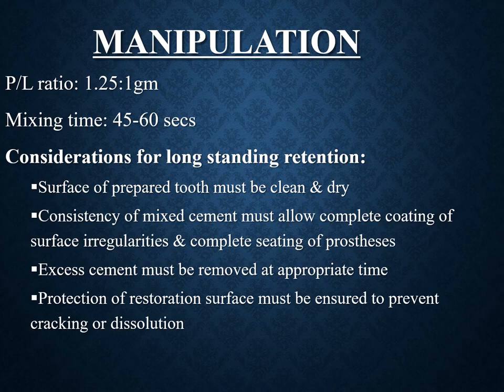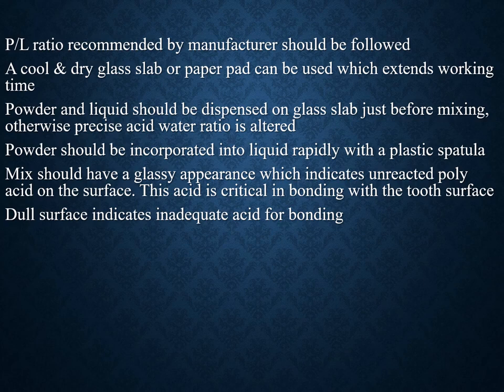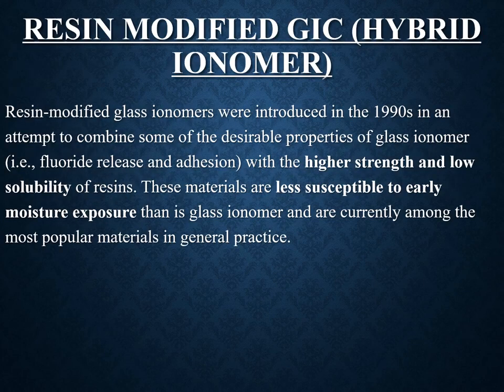Protection of the restoration surface must be ensured to prevent cracking or dissolution. The manufacturer's recommended powder-to-liquid ratio should be followed. A cool, dry glass slab or paper pad extends working time; powder and liquid should be dispensed before mixing, otherwise the acid-base ratio will be altered. Powder is incorporated into liquid rapidly with a plastic spatula; the mix should have a glassy appearance indicating unreacted polyacid on the surface. A dull surface indicates inadequate acid for bonding.